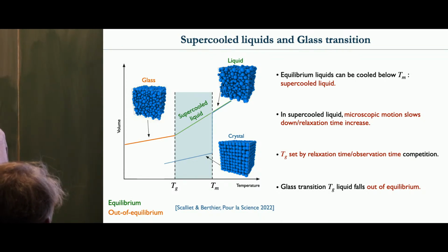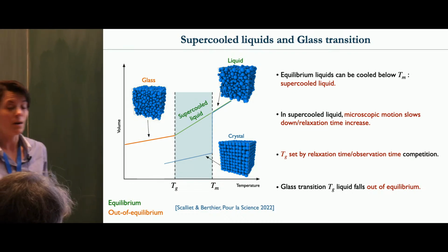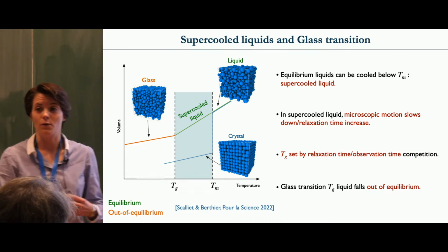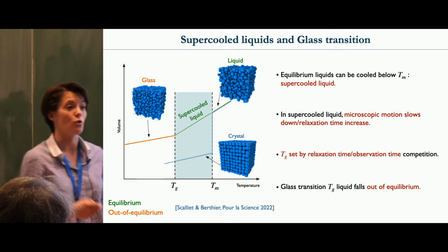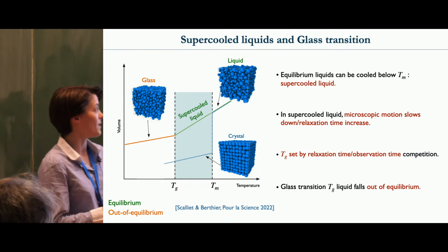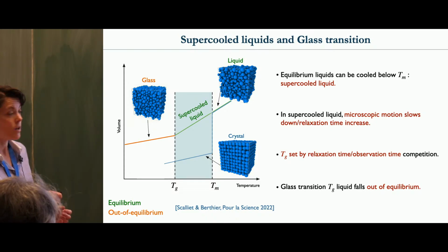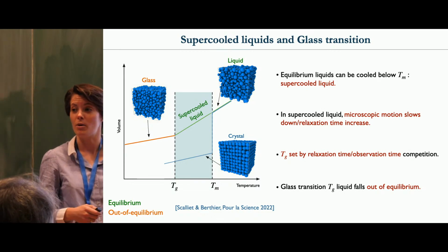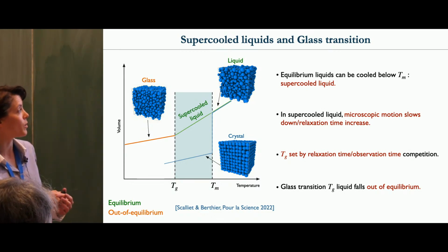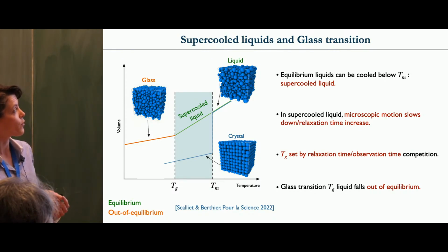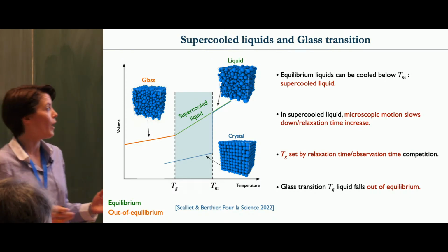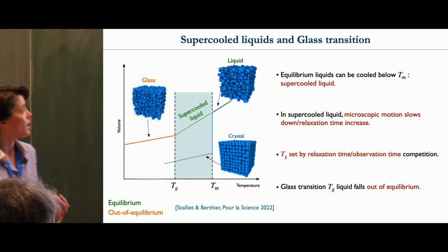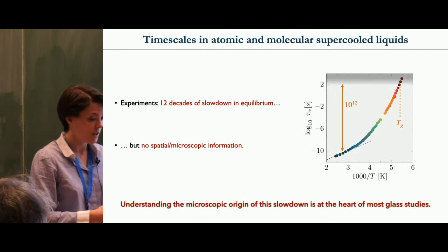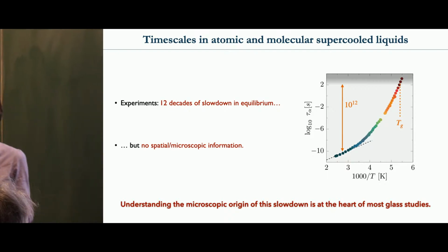So you take a liquid and you cool it rapidly enough to avoid the crystal. And what we have been discussing is the fact that the dynamics slows down dramatically, and we want to understand why this happens. So this is equilibrium physics. We're not yet in the glass, which happens at the glass transition temperature Tg, which is determined empirically as a relation between the microscopic time for the liquid to flow and the time that you have to observe the liquid. So I want to discuss this region here, and I want to go back to experiments.